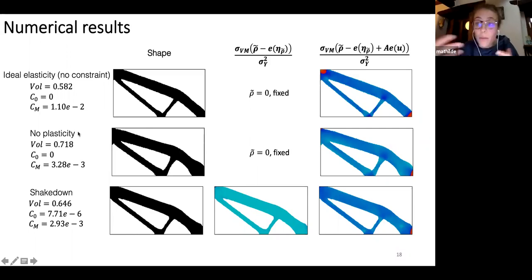And applying the Von Mises constraint as we did in the first part, we see that the bars are thickened. So as we have already seen, the volume is increased, but the Von Mises constraint is decreased. And we see here that, indeed, we have no more red here and a lot less here. And then we apply the shakedown constraints and we see that the bar is thickened a little. We have some modifications here too, but the volume is increased, but not as much as it was under the non-plasticity constraint. We see that a residual stress is created within the solid, but this residual stress remains within the circle at each point because you see that we don't have any red on the figure.